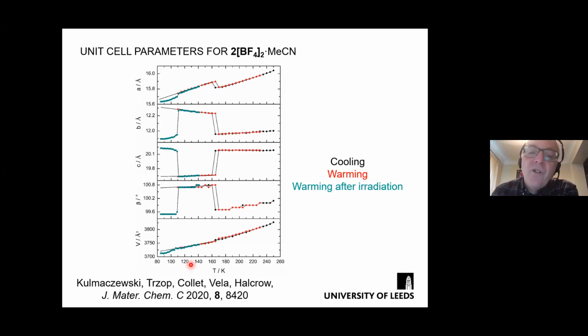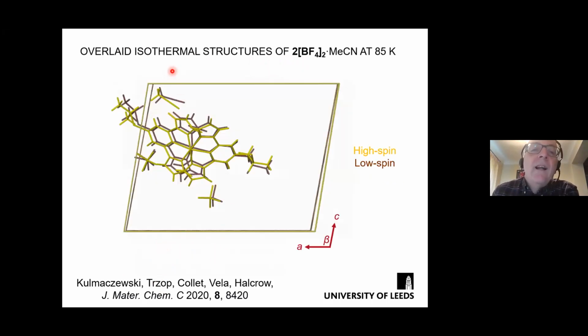Another thing to notice is that this guy, the acetonitrile solvate, this is looking at the relaxation in the crystal using unit cell measurements. And the unit cell volume actually increases a little between the high spin and the low spin state. We get a negative thermal expansion almost between the high spin and low spin. The low spin has a larger unit cell than the high spin. And this is the opposite to the normal trend, and it's very unusual. And it happens